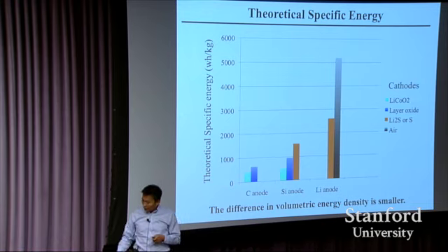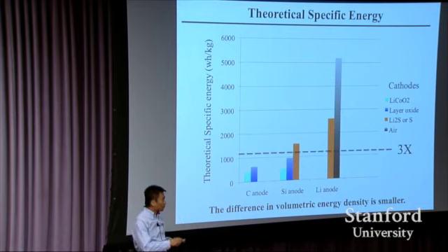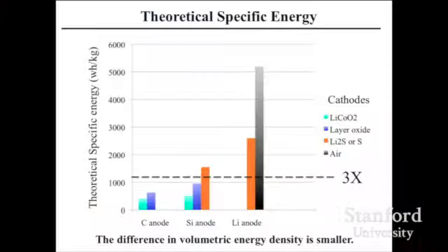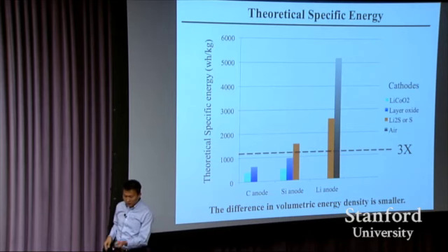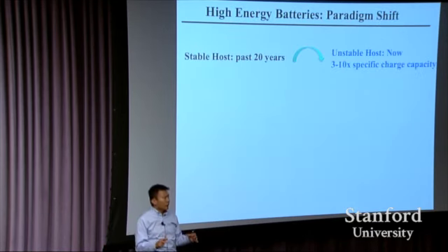Now you want to look at the 3 times of energy. It's possible. Silicon anode with a sulfur, lithium sulfide combination can give you 4 to 5 times or more energy. And then lithium metal with sulfur, lithium with air potentially can give you a lot more. So from the limit standpoint, from the chemistry standpoint, it is possible. And now we see whether we can make this battery chemistry work. That's the key question.